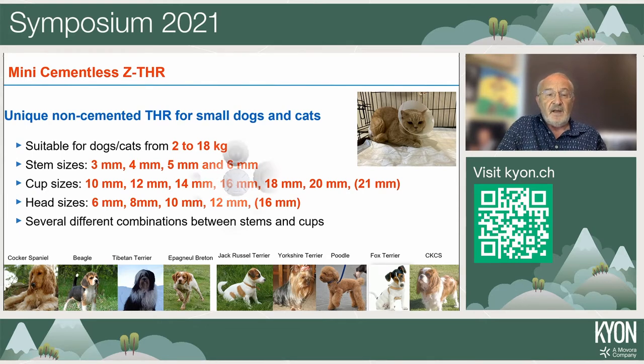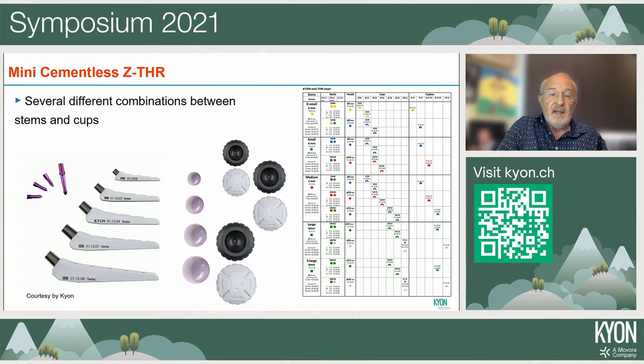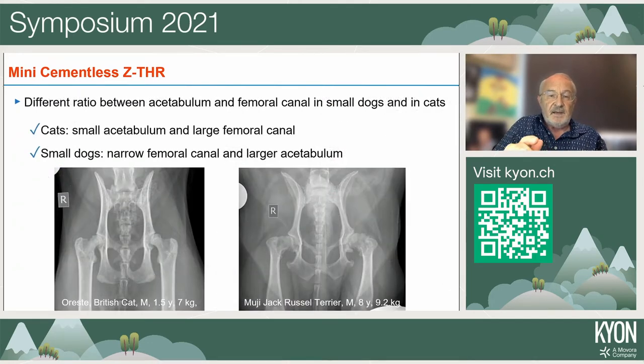So we have several different combinations between stem and cup size because small animals have quite a variation in the relationship between the acetabular size and the stem size, the femoral size. So the 3 millimeter stem can move forward for the cups that are suitable for the 4 millimeter and vice versa. That is very important, as I can show you in this example. On the left side, you see a cat with a large femoral canal and a very small acetabulum. And on the right side, we see a Jack Russell with a quite large acetabular size compared to a very narrow femoral canal.